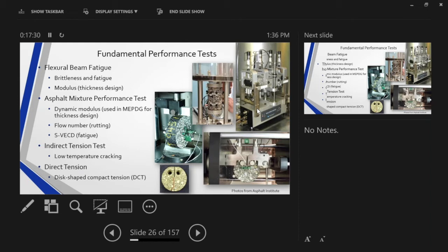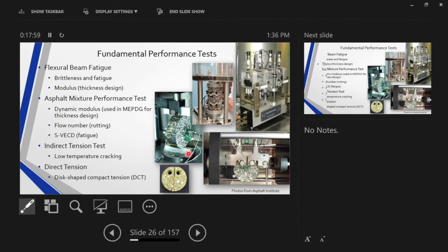What you're looking at here are very fundamental tests, whether it's beam fatigue or things such as dynamic modulus, indirect tension or low temperature creep, and with the extensometers that you see on the far left picture with the green gauges. Those gauges are very expensive. You're looking at $4,000 to $5,000 just for a set of gauges for a sample, but they allow us to measure at very, very small levels of movement. Do we need that for everything that we're doing on production? No, but we need this in the laboratory, and then we naturally have to move that out to the field.